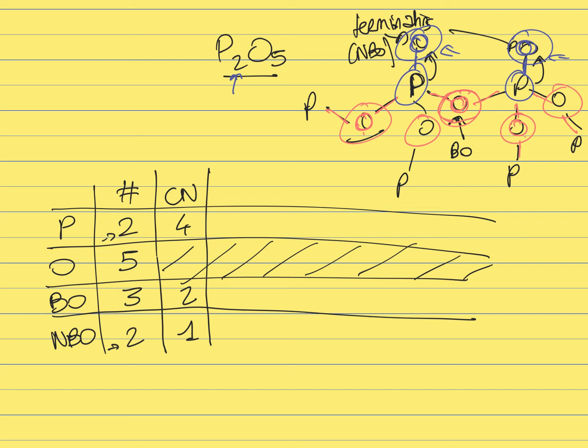But this oxygen atom here is fully contained in between the 2 phosphorus atoms. But those oxygen here are going to be shared with some other phosphorus atoms. So they should be counted only half. So that's the reason why you end up with 1 oxygen, 1 half, 1 half. So that's another oxygen, and 1 half, 1 half. That's another oxygen. So you end up with 3 oxygen per formula unit of P2O5.